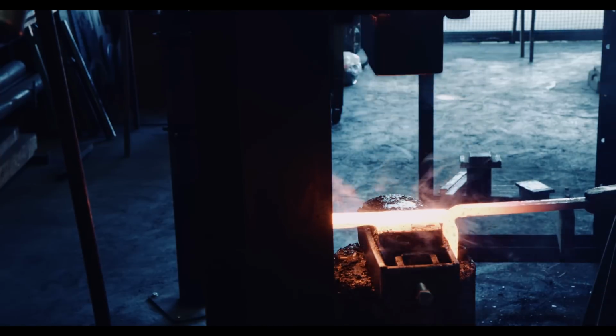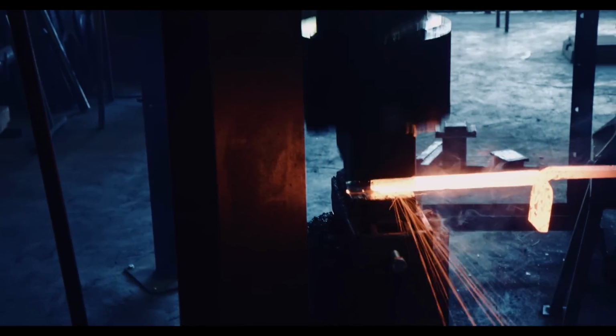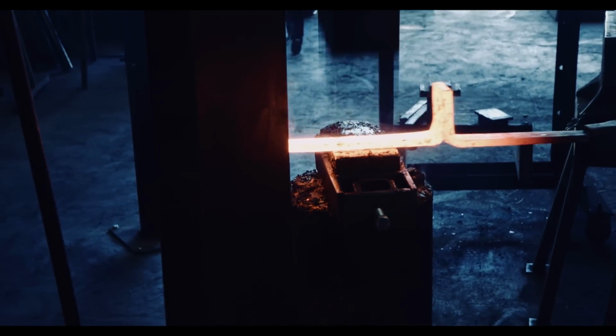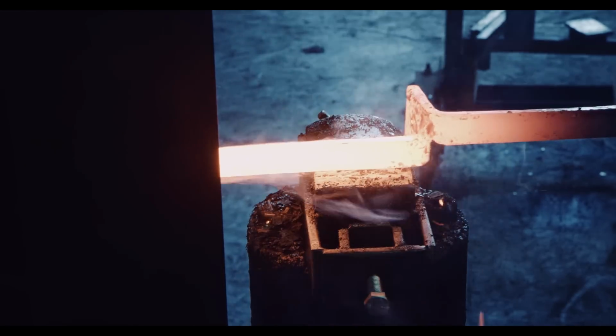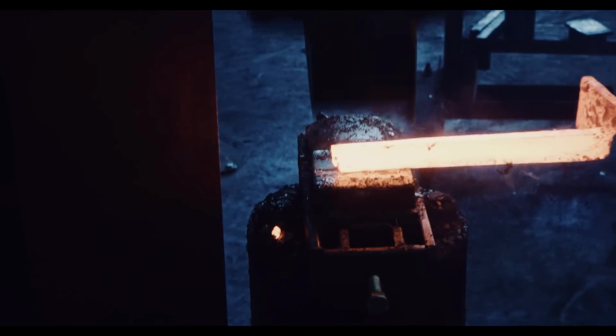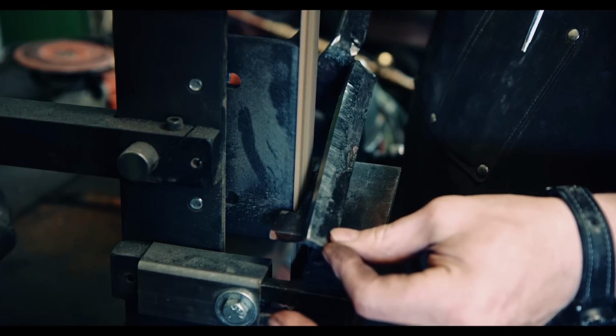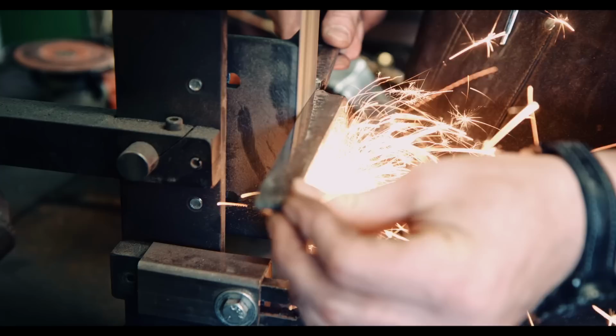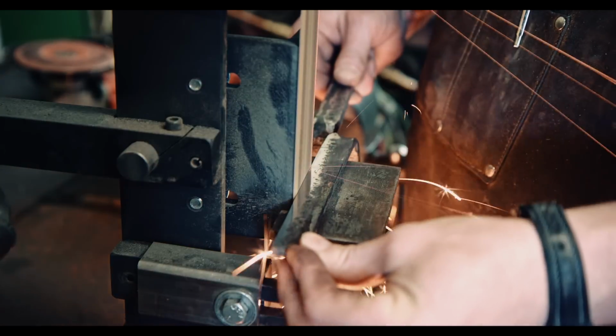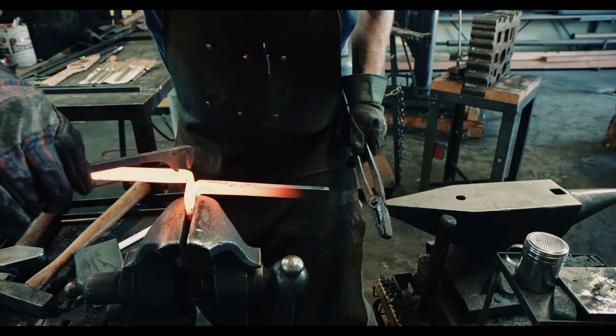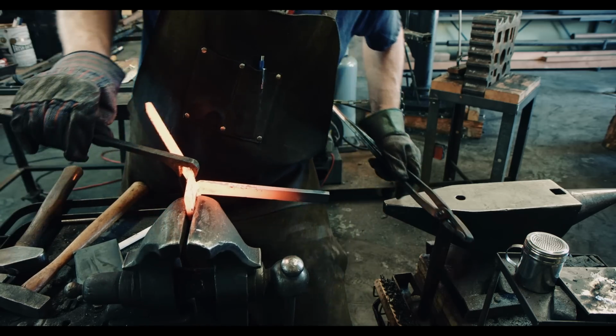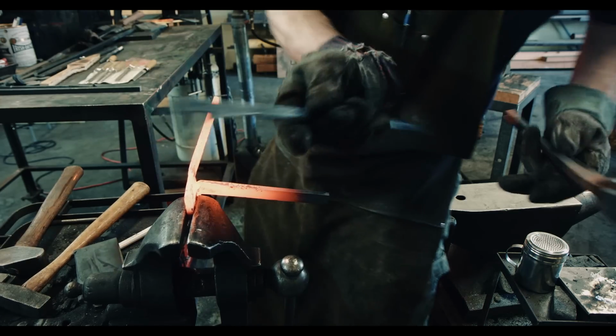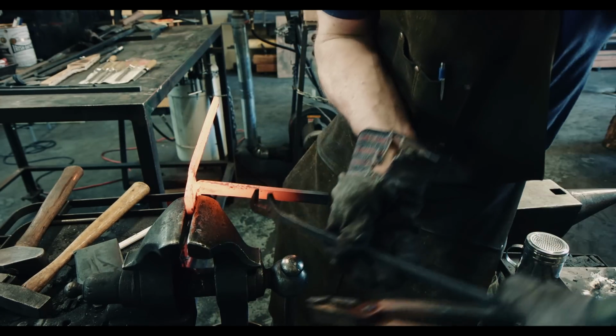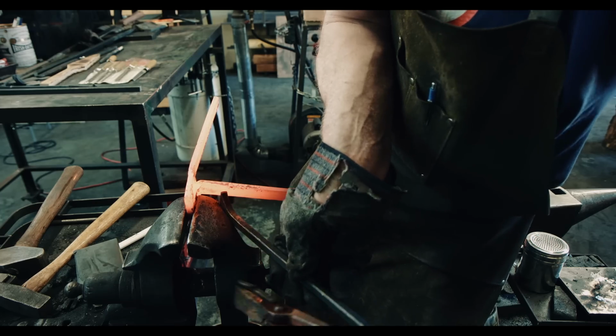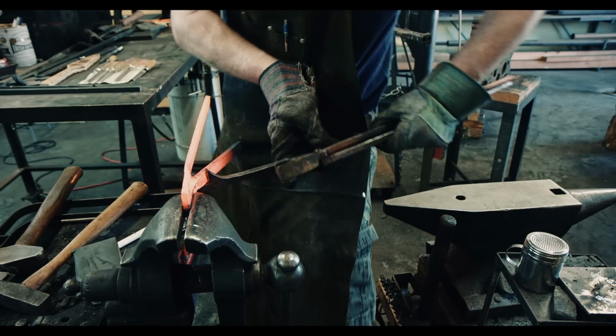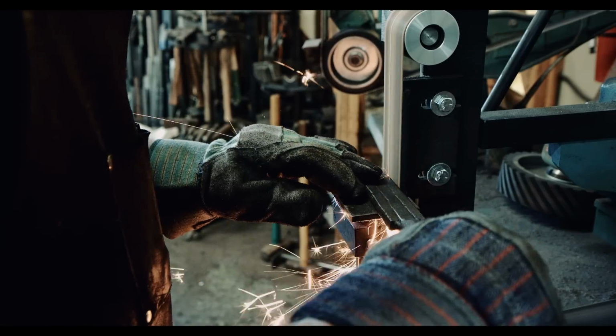The wrought iron has been combined with the high carbon edge steel and is now being forged to the same width and thickness to prepare for more forge welding. I am making sure that the surfaces are straight and free of scale. A great benefit of steel is that it is very malleable when hot. This allows me to bend the arms back into place. All of these manipulations are a little bit scary since I don't want any of the forge welds to come apart, and wrought iron can be a little bit tricky.